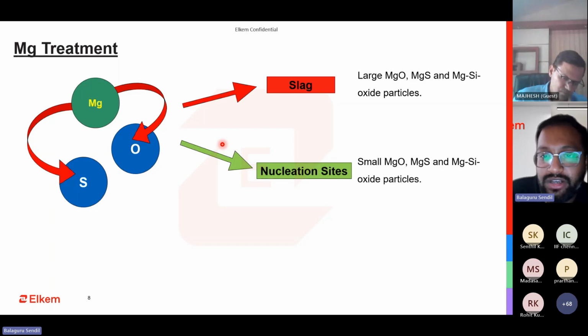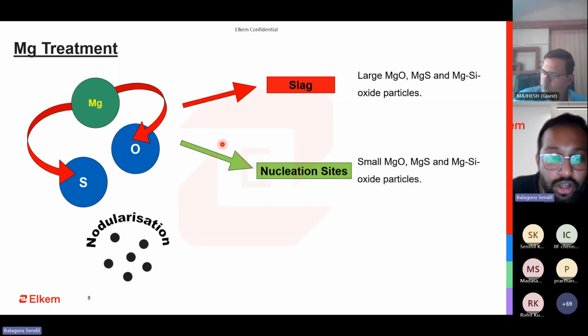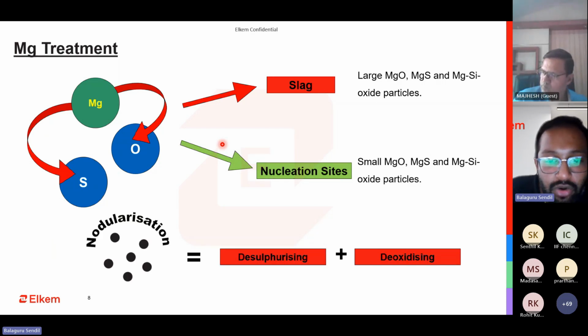These MgO and MgS particles are 1 micron in size and very stable. But unfortunately, if more magnesium is added or more sulfur is added, then they have the chance of agglomerating together and moving out. So basically, nodularization is nothing but desulfurizing and deoxidizing. So this is the basic fundamental of magnesium treatment. The key factor here is that you need to maintain a minimum amount of sulfur. If the sulfur level goes beyond a certain level, then that is also a risk.